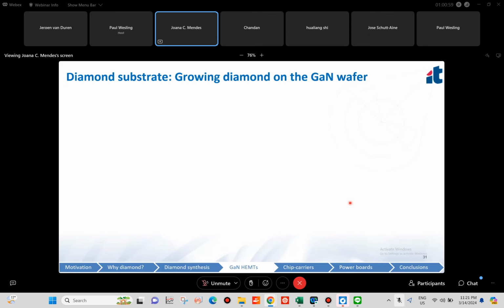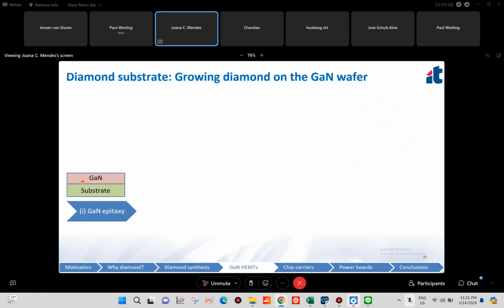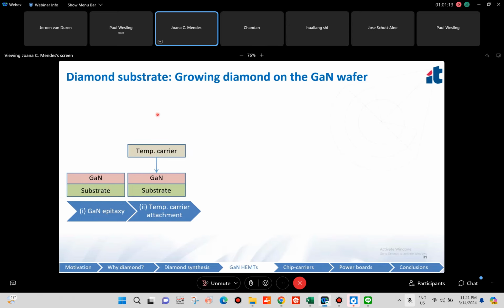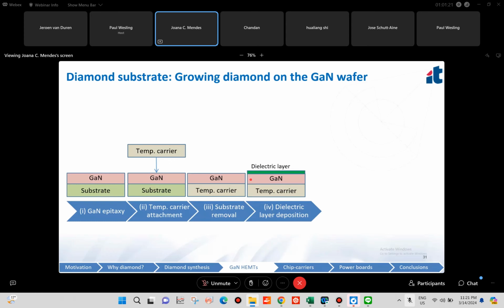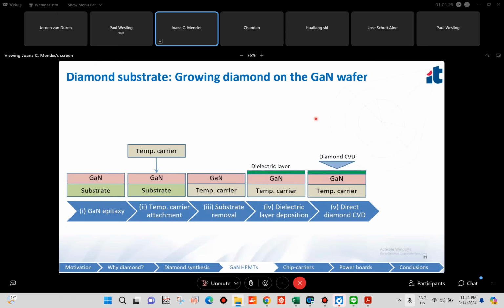With respect to diamond substrates, we can grow them on the back of the GaN wafer. So here we begin with the GaN wafer, typically GaN on silicon wafer. Then we just attach a temporary carrier on top of the GaN wafer. We flip the wafer over and we remove the substrate. And then we deposit a thin dielectric layer for protection of the gallium nitride layer. And then we just grow the diamond directly by CVD. And then we remove the temporary carrier and we are left with the GaN on diamond wafer.